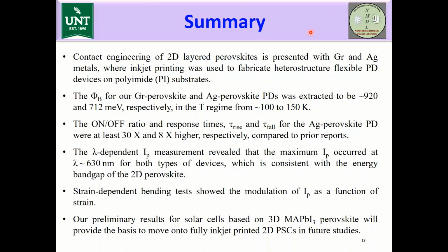So to summarize, we have fabricated fully inkjet-printed two-dimensional perovskite photodetectors using graphene and silver inks on flexible polyimide substrates. The on-off ratio and response time for these perovskite photodetectors were found to be quite higher than prior reports. Also, our second part of the work, which is related to the development of two-dimensional inkjet-printed perovskite solar cells, is in progress. We are currently optimizing the 3D perovskite solar cell structure, and we are continuously working towards that goal.